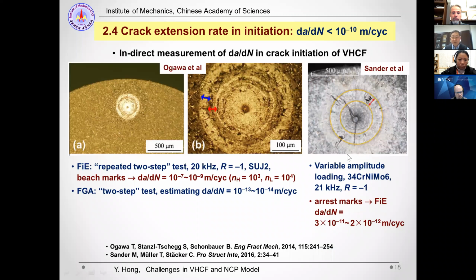And another example of indirect measurement uses variable amplitude testing for a structural steel, and this result is for 34CrNiMo6, a structural steel, and the result is between 10 to the minus 11 and 10 to the minus 12 meter per cycle for the fisheye.